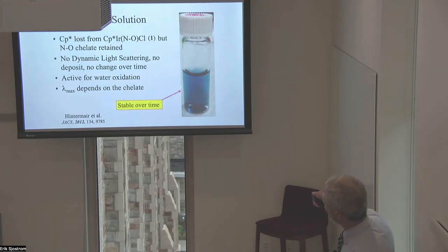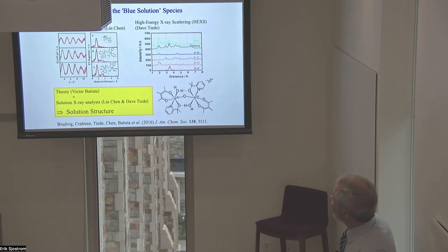So this is the blue solution. It's stable. Make it, put it on the benchtop, room temperature, stable for weeks. So it's a very stable molecule. We know that the Cp* group is lost. It's oxidatively modified. There's no nanoparticles being formed over time. And as I mentioned, very active for water oxidation. And we know it still has the chelating group because the absorption depends on which chelating group is put on other ones. And so this solution, however, has been incredibly difficult to characterize in detail.